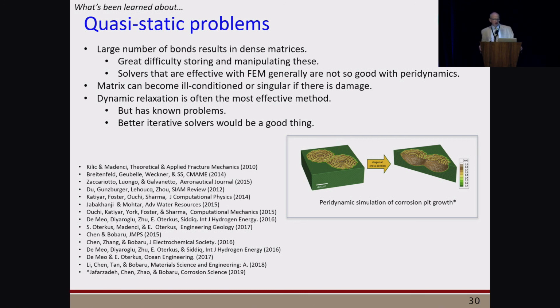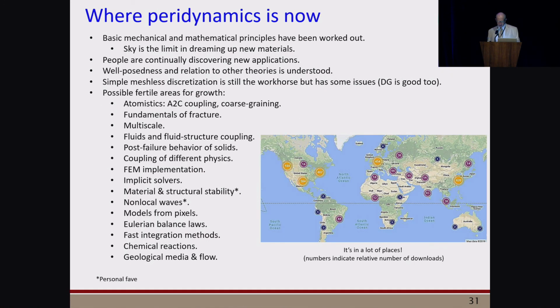Another thing we've learned is that in trying to solve quasi-static problems, the fact that in peridynamics there are so many of these bond interactions for each node, you get matrices that are much more dense than you would in a finite element code. And as far as I know, tools for dealing with these dense matrices or even storing them are a challenge. And as a result, most people continue to use dynamic relaxation, which is reliable, but it has some known limitations.